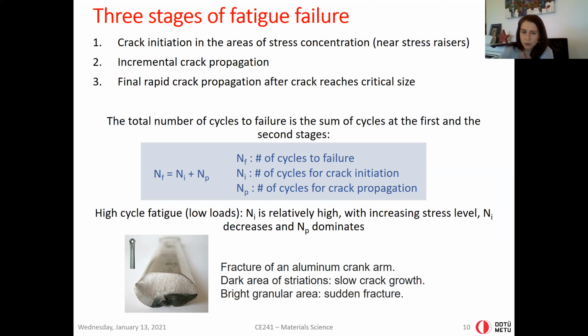At low loads, which is also known as high cycle fatigue, initiation is relatively long. So you need to repeat many times to initiate the crack. But with increasing stress level, the initiation actually becomes easier and propagation starts to dominate the number of cycles. Here on the bottom, you see an image of an aluminum crank arm fractured due to fatigue. The dark area shows slow crack growth, and the bright granular area is the sudden fracture.